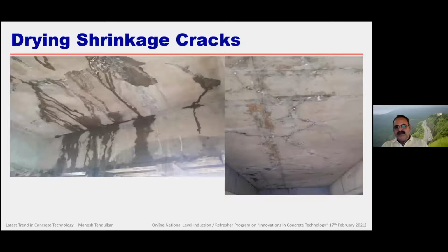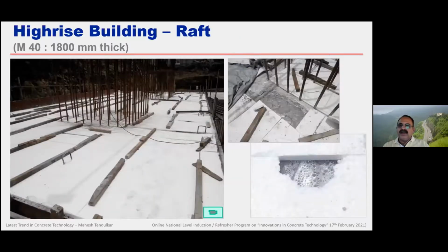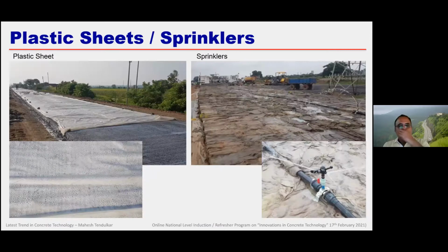So otherwise, this is a typical scenario of slabs where we feel many slabs are leaking during the curing period itself. This is purely because of the shrinkage crack, nothing to do with concrete properties or cement properties. It is purely a lack of curing, or rather, lack of early curing. Just before coming to the end, I want to show you how it is based.